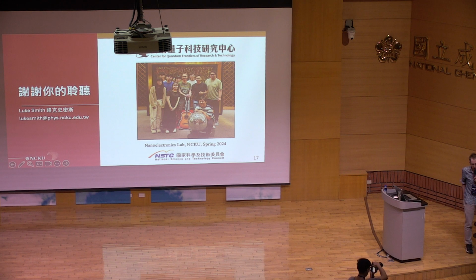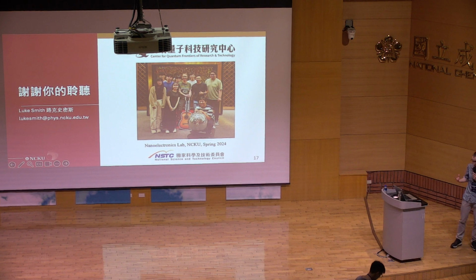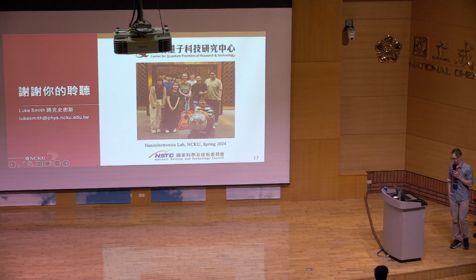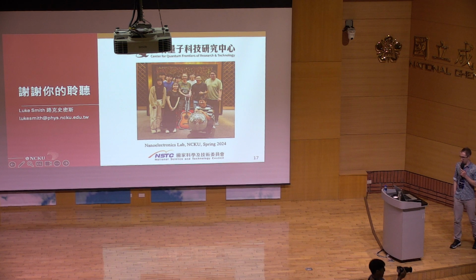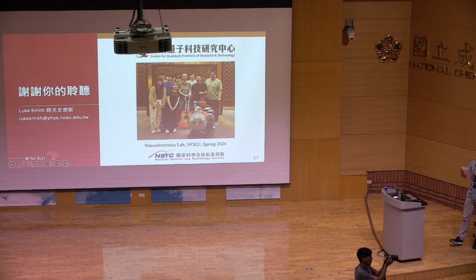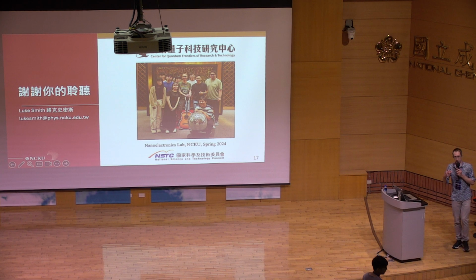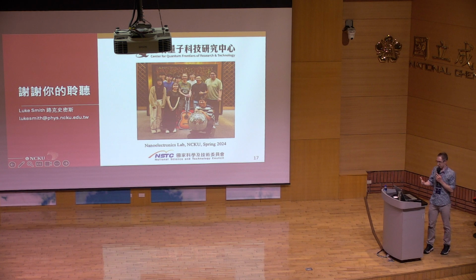So far, in our measurements, we see an increase in the mobility before and after the oxidation, and the mobility increase is because we have a higher carrier concentration. In terms of damage, because we see the increase in mobility after oxidation, that's enough proof for us that this process isn't significantly damaging the sample.